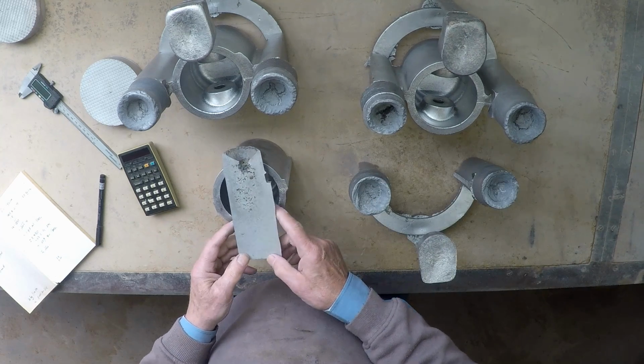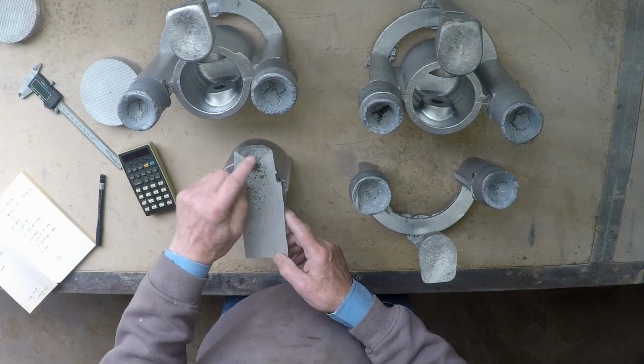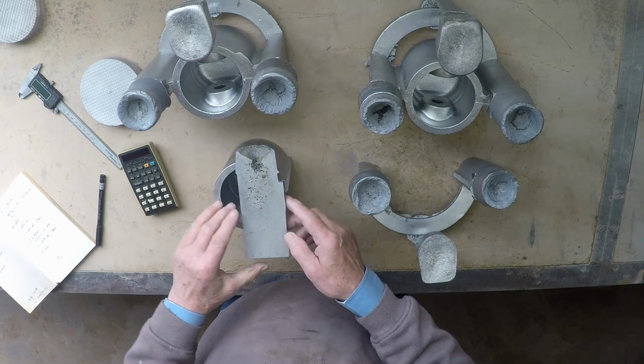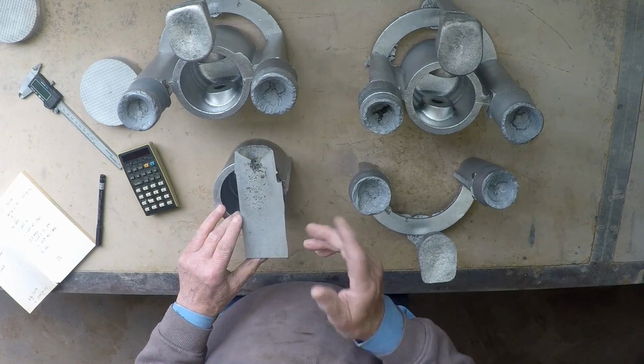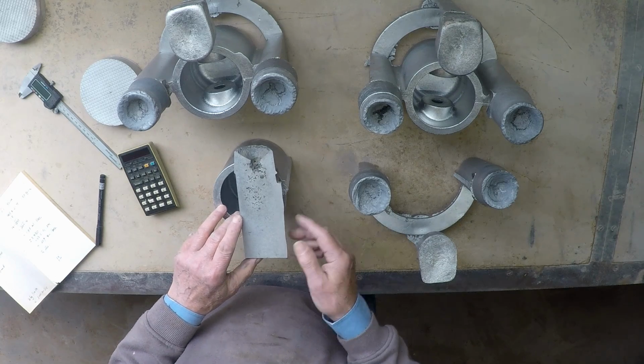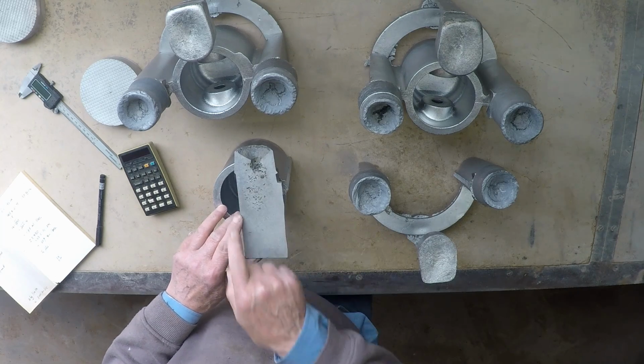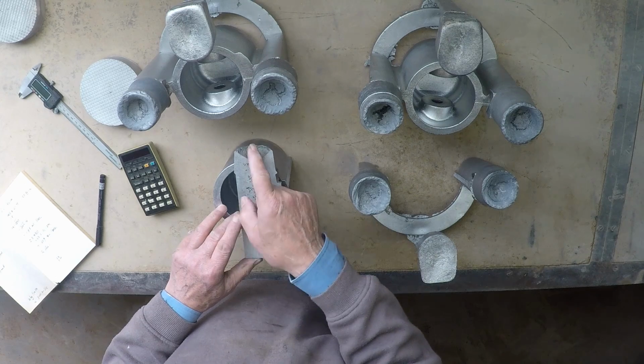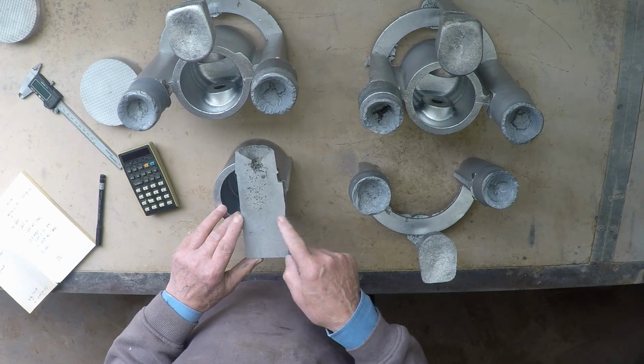It's a centerline sort of a feeder, but it's a bit messy, and this one cut off an earlier piston. I have slit, roughly polished, and then etched in caustic to bring the porosity out. The only danger, of course, is that the porosity moves like this into the piston.